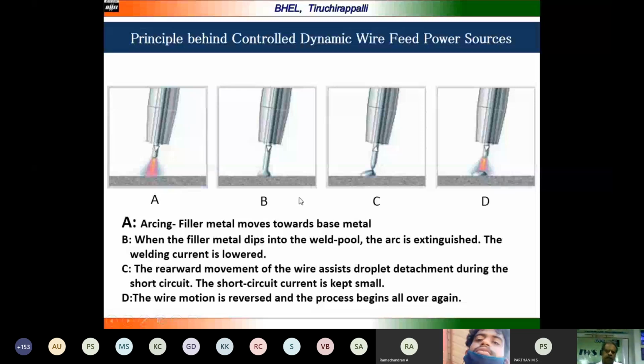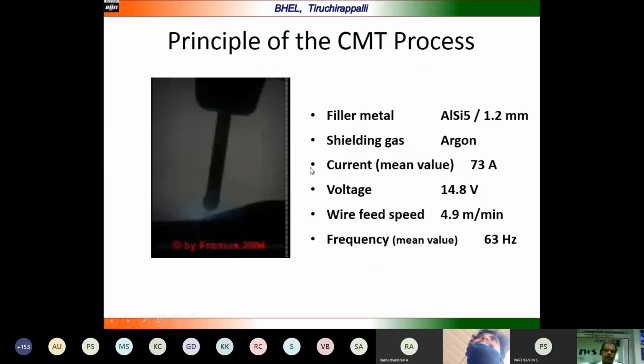The video shows you how that CMT process is used. It is for building with filler metal aluminum Si5 1.2 mm with argon shielding gas, current of 73 amps, voltage of 15 volts, wire speed 5 meters per minute, and frequency of 63 hertz. These parameters are used, and then it has been developed for years and is available. Many research institutes and industries have this process now, especially automotive industries are using this process.